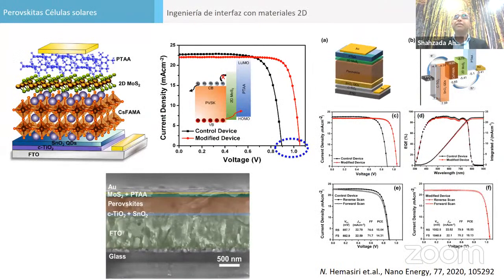Basically, to increase the stability and align the bands, we have used 2D materials. There are plenty of 2D materials other than graphene: MoS2, WS2, and different types we have used. We placed a very thin layer of 5 to 10 nanometers of MoS2 between the hole transport material and the perovskite. This protects the perovskite from environmental attack, improves the stability, and aligns the energy levels. You can see the energy level is aligned and the VOC is increased, by almost 180 or 190 millivolts, and we achieved close to 18% efficiency. This is a very good efficiency because we used PTAA, polytriarylamine, which is more stable, and it was undoped. So with an undoped HTM, this is a very good efficiency.